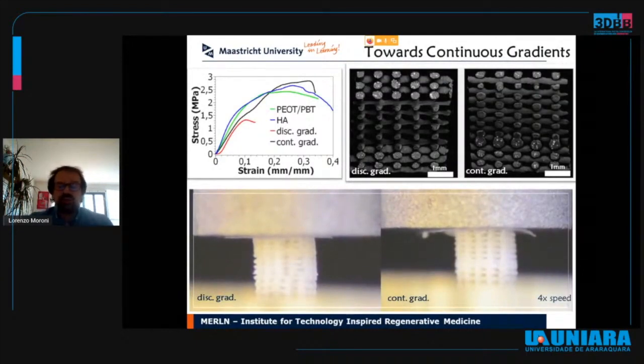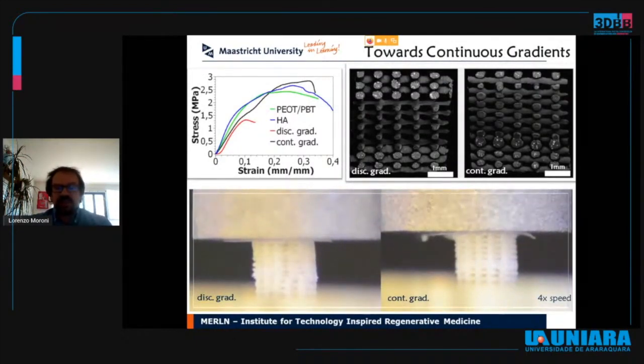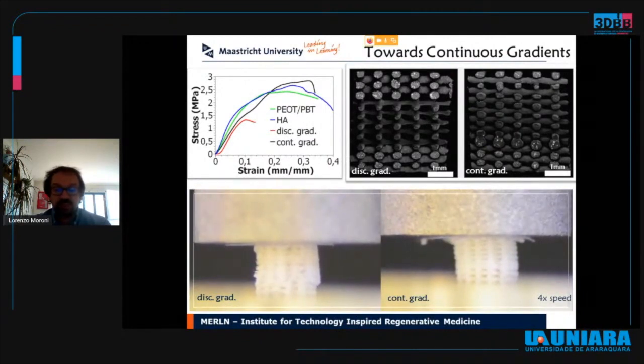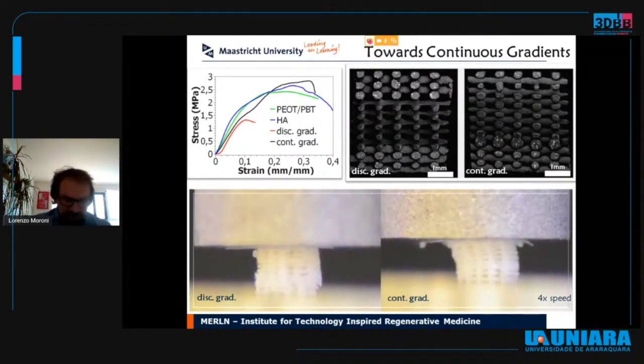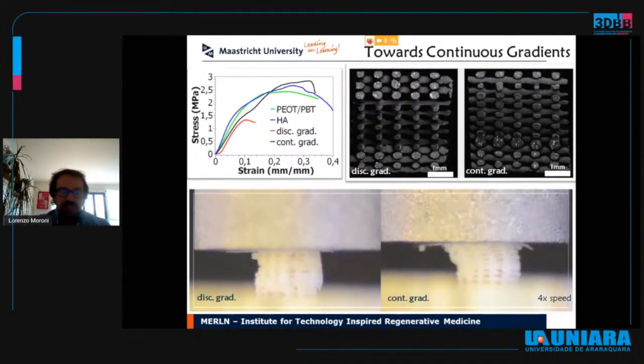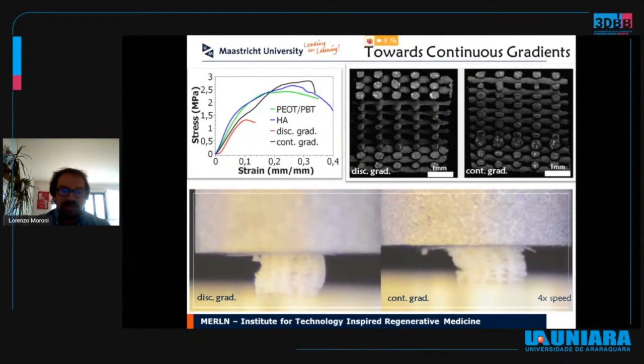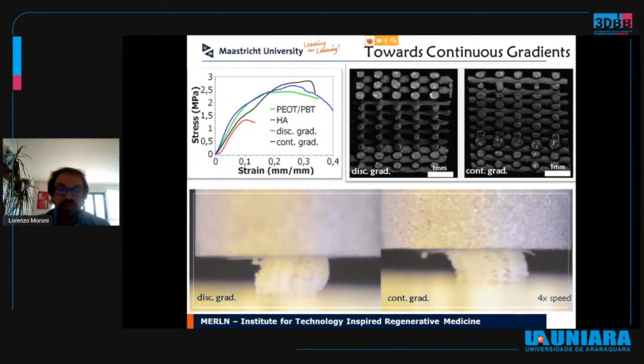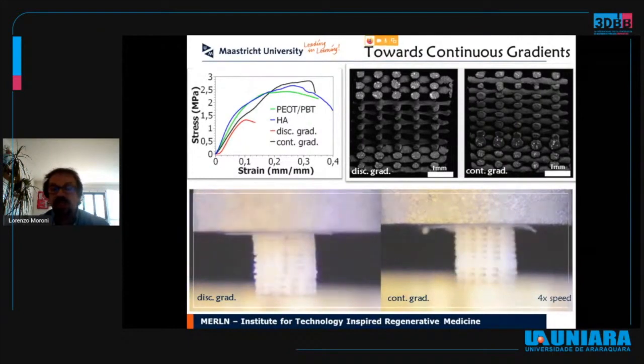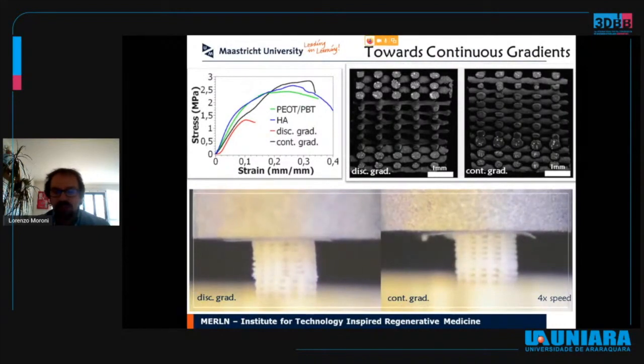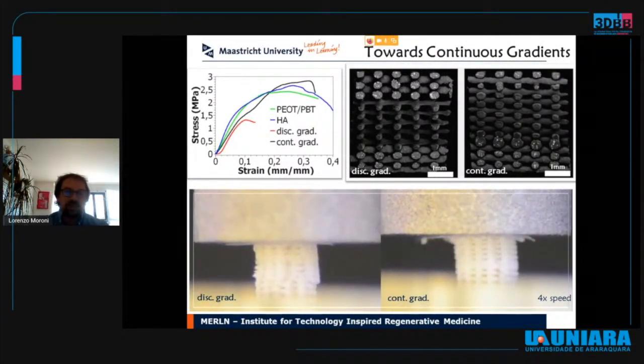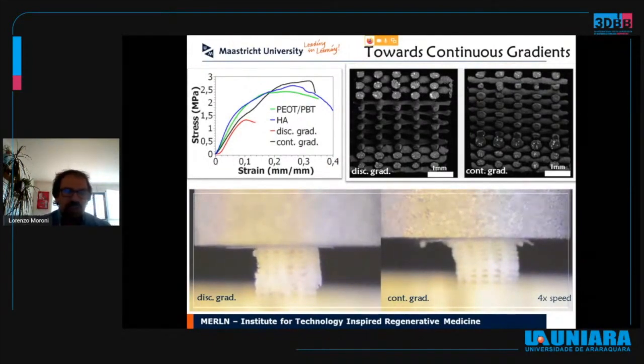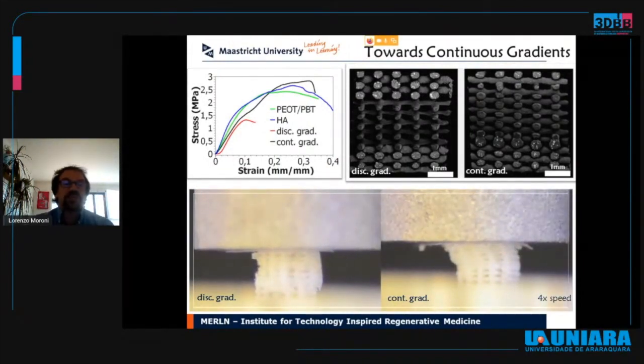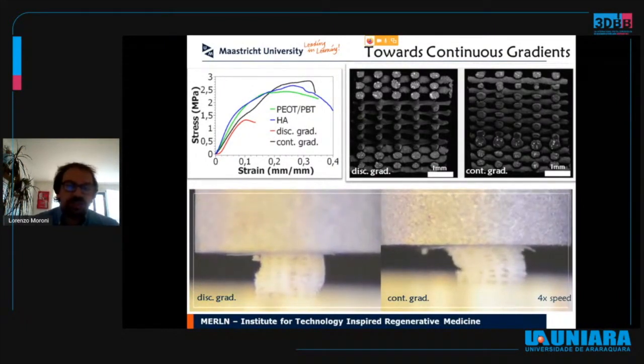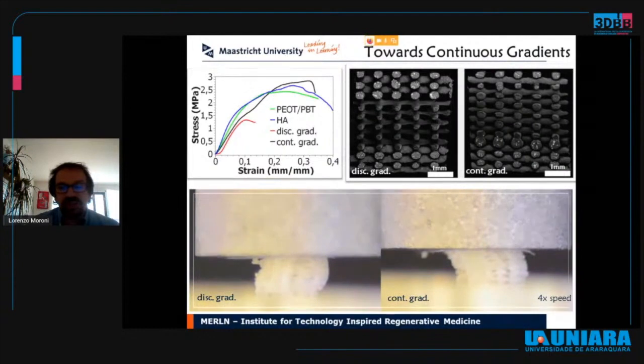Now, is this continuous gradient really any better than discrete gradients? From a mechanical point of view, this seems to be the case. What you see here also in the video is that while the discrete gradients here on the bottom left video tend to fail progressively at each different sub-region of the scaffold, in the continuous gradient, we can compress the scaffold homogeneously and continuously throughout its volume before it fails. This is also represented in the stress-strain curves, where you can see that the scaffolds have a much higher strain at break and a much higher stress at break compared to the discrete gradients.